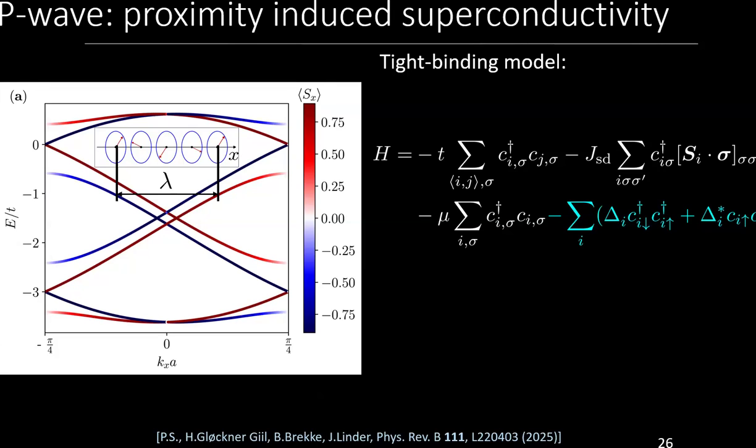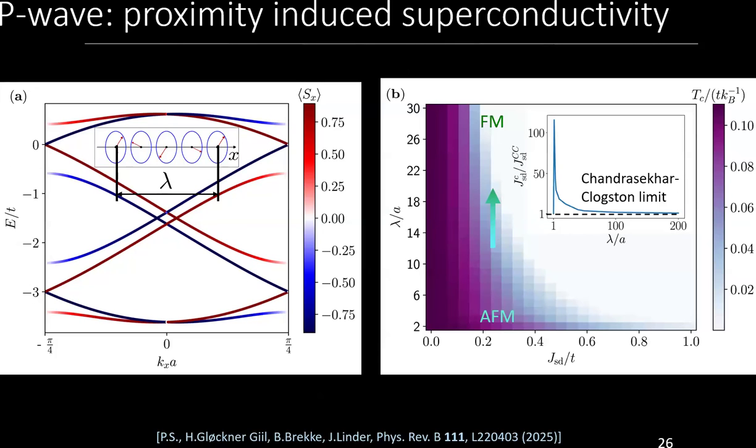We can consider a pairing between terminals, and what do we have? And actually, how do we form our p-wave magnet? We consider an even more generic type of magnet, which is just a helical magnet. It's composed of chains with rotated spins of a certain period. The period is essentially the distance between sites with spins pointing in the same direction. In the example we considered before, the period was 4: spin up, spin to the left, spin down, spin to the right. Period 4.